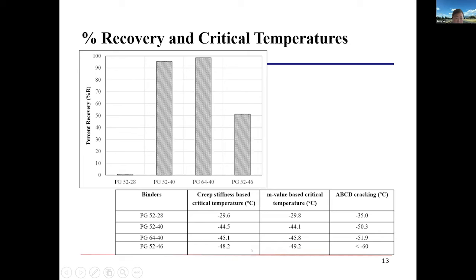And here in this table, we summarize the temperatures based on the criterion from the BBR, the creep stiffness and the m-value, and also the cracking temperature directly measured from the ABCD device, the asphalt binder cracking device. So it can be seen that all HPABs have much lower critical cracking temperatures, though there are differences due to the mechanisms behind the testing methods.